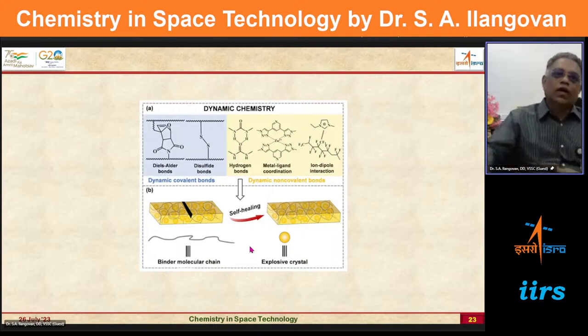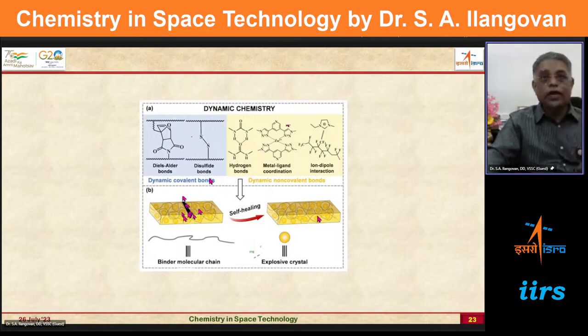So wherever the systems, whatever we are having, this line is nothing but a crack that is getting formed. So we can incorporate some of these materials which are enclosed, like you can see here, the sulfide cross-linking is there. Disulfide reaction you would have gone through. So now nitrogen-rich materials with the complex is also there. So the ligands are engulfed into the coordination materials, coordinated complex. So once there is a crack, these materials are getting exposed, then it releases the reactant in situ, so that it is able to get healed up, right? So once there is a crack, the materials are exposed, then it is able to bring in the new bonds in situ. So that facilitates or brings out the self-healing aspects.